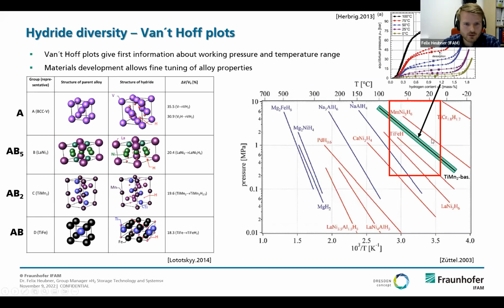So the hydride diversity is very, very huge. A lot of materials absorb hydrogen or adsorb hydrogen on the surface. These are just some examples of interstitial hydrides, so metallic hydrides that are very cycle stable, for example, that can be cycled a few thousand times. This can be titanium manganese based hydrides like these ones here, or titanium iron based hydrides.